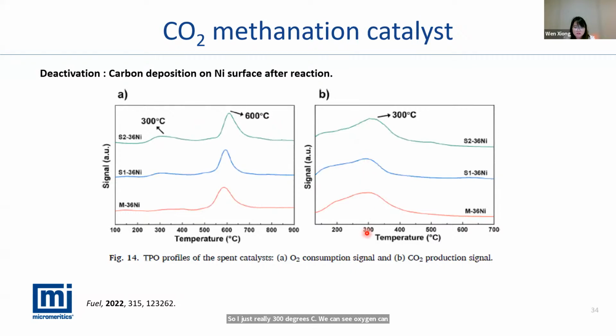This means carbon deposition on nickel has happened and can be burned off as carbon species at 300 degrees C. Okay, we do the same thing at 600 degrees C, since we see the oxygen consumption at 600 degrees C. At 600 degrees C, we are not able to see any CO2 produced. So this means the oxygen consumed at 600 degrees C oxidized the nickel catalyst. So that's why we are not able to see CO2 production.